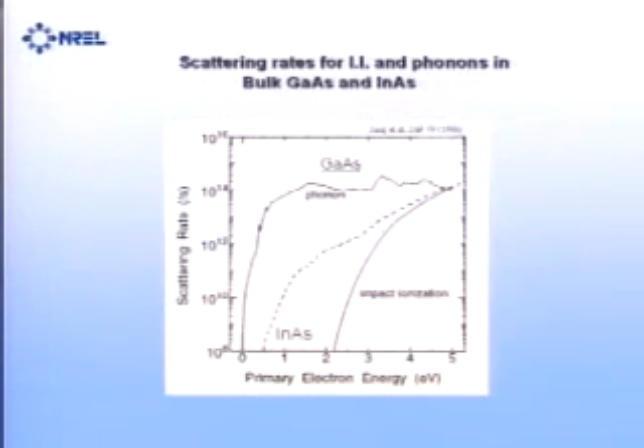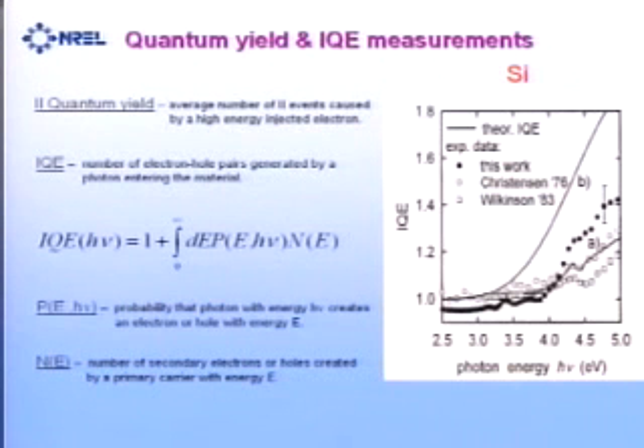And therefore, in addition to that, the rate of impact ionization requires, say, for silicon, going to about 5 times the band gap. So between the two, it turns out that impact ionization, say, for silicon, doesn't even begin to show up until you're 4 to 5 times the band gap out here in the ultraviolet. And even then, you only get maybe 20% increase in quantum yield. So for bulk semiconductors to use this for PV, it's